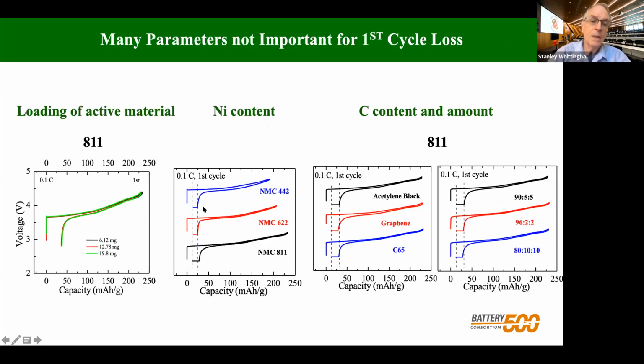What we're doing here is, after a constant current charge and discharge, we're now holding it at 2.8 volts. And you can see we're getting some of this capacity back, which is suggesting to us this is a rate limitation. We then looked at different sorts of carbon: acetylene black, graphene, this specialized C65. Again, no difference. And it made no difference how much carbon we had in there. So this is the amount of carbon, amount of binder, and the active material. Whether this was 2% or 10%, it did not affect the capacity of the active material itself. So these were not important parameters.